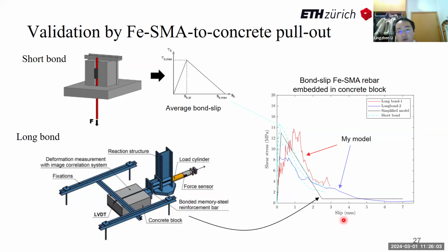But if using my model, we just need the force-displacement behavior of the bonded joint with long bond length and the stress-strain behavior of the steel rebar or SMA rebar. Then in one shot, I can analyze the local bond slip behavior, shown as this red curve and the blue curve, which is very similar to the analysis result of my colleague Bernhard.